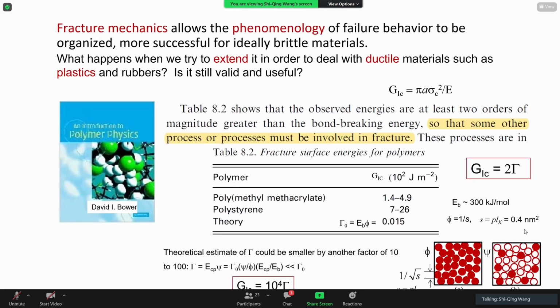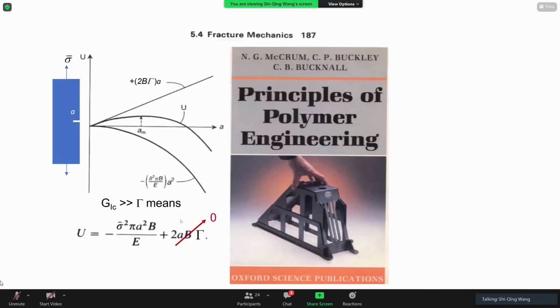So far so good, except when we look at our polymers, much has been discussed on PMMA, polystyrene, you find this G, unlike what Griffith likes to argue, is actually much larger than surface fracture energy. Thousands of times, or if you use my estimate, even larger than a fracture surface energy. So this makes the argument very problematic in terms of what insight we can have. In fact, this being much larger would imply that you actually have no quote-unquote nucleation barrier, meaning this fracture should occur at any level of crack size, because this line basically goes to 0. You only have just this term dominant. Well, it looks very problematic.